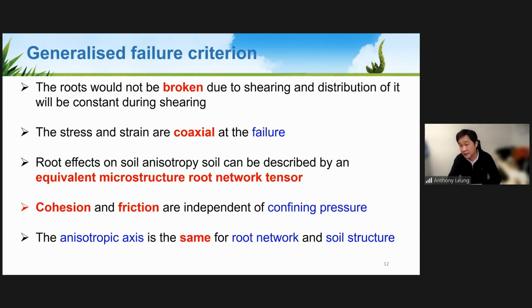Now, in our experiments, we didn't observe any breakage of roots. So we couldn't use the philosophy or the assumptions made by the previous root reinforcement model by Wu, the fiber bundle model. So we have to assume all roots were not broken during the shearing. And one further assumption we need to make is the stress and strain are coaxial during failure. And the root effects on the soil anisotropy can be described by an equivalent microstructure root network tensor. So I will introduce that later.